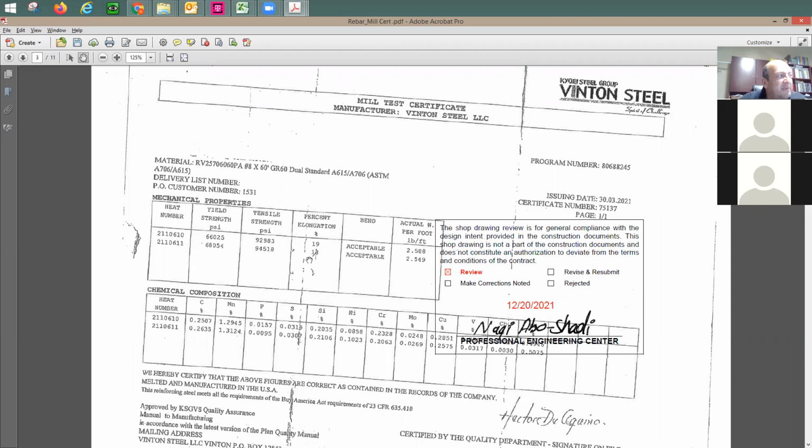Now the steel strength is going to be very critical because you know that I'm working here with A615, which is for gravity. But if you would like to work with reinforcing bar for seismic members, it has to be the A706. In the A706, it is controlled. You cannot just go to any value. So in the 615, your minimum is going to be 60,000. Your ultimate, there is no limit, but yours is going to be above 90. In the 706, you have limits. You cannot go above 68.